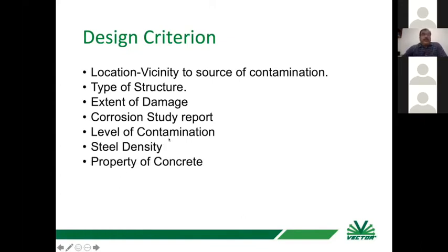So you need a different type of design based on the level of contamination. And then steel density. Please don't misunderstand steel density as the weight or diameter or cross section of the steel, which is a structural parameter. When it comes to durability parameters, you should know the surface area of the steel, because we want to protect the surface of the steel from corrosion. Properties of the concrete also come into the picture. If you have a very high grade of concrete, or use various types of fines or replacement of cement, then the resistivity changes. Or if you have another type of concrete, then resistivity changes. You should consider the properties of concrete for the design criteria.